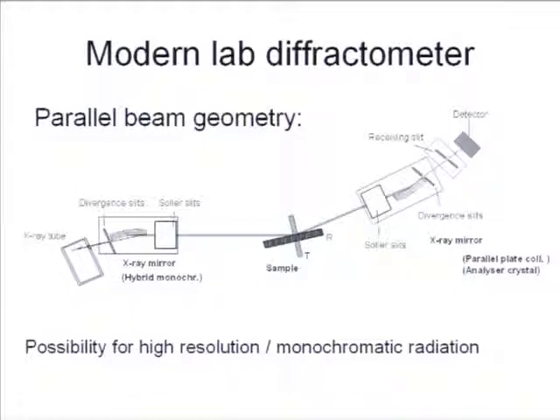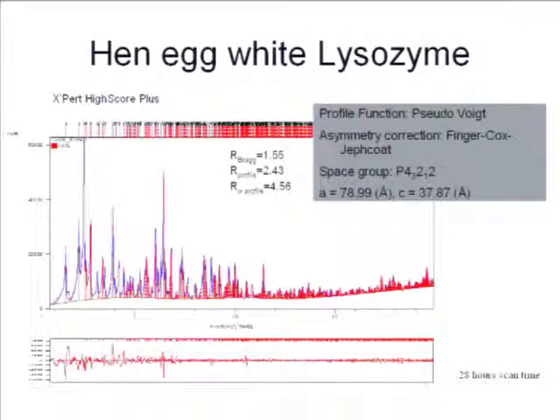So one configuration that was very successful for a lab diffractometer is shown here. It has an X-ray tube, and it has extra sets of divergence and solar slits before and after the sample. We measure in transmission usually, and there is an extra receiving slit here before the detector, plus focusing mirrors and analyzer crystals. Without this configuration, we haven't managed to get good data. With this setup, we got surprisingly good data for lysozyme. This measurement was done at Panalytical in Almelo, but I'm sure that if we use the latest, the D8 from Bruker, probably we'll get an extremely good pattern as well. This corresponds to the tetragonal phase of lysozyme. Quite good data, good enough for indexing, 28-hour scan.